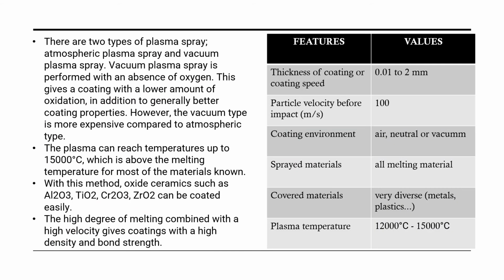There are two types of plasma spray, which are atmospheric plasma spray and vacuum plasma spray. Vacuum plasma spray is performed with an absence of oxygen. This gives a coating with a lower amount of oxidation in addition to generally better coating properties. However, the vacuum type is more expensive compared to the atmospheric type. The plasma can reach temperatures up to 15,000 degrees, which is above the melting temperature for most of the materials known. With this method, oxide ceramics such as alumina, titanium dioxide, chromium oxide, and zirconium oxide can be coated easily. The high degree of melting combined with a high velocity gives coatings with high density and high bond strength.